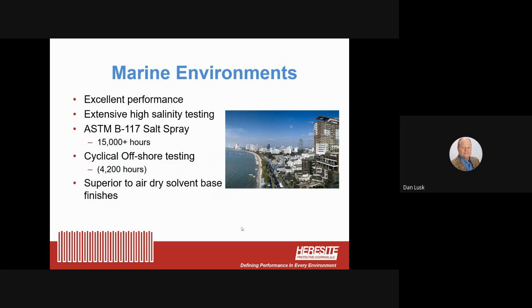We have extensive salt air testing, both real world and in the laboratory. The ASTM B117 salt spray hours on this are 15,000 plus hours. That's compared to under 5,000 hours for our other air dry products. It does well in cyclical offshore testing, and really it's superior to the air dry solvent-based finishes in just about every test that we've done.